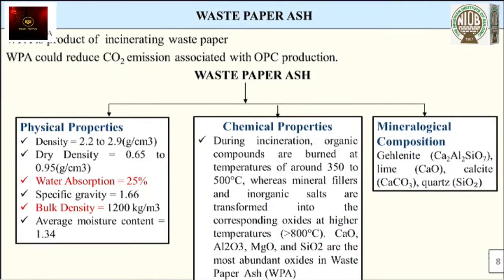Now, waste paper ash is generated from the incineration of waste paper. Waste paper ash could reduce the CO2 emission associated with the production of Portland cement. Now, we can see the analysis of the waste paper ash. We have the physical property analysis. The density is stated as between 2.2 to 2.9, and also the dry density, water absorption, specific gravity and bulk density. Also, the average moisture content is stated here.